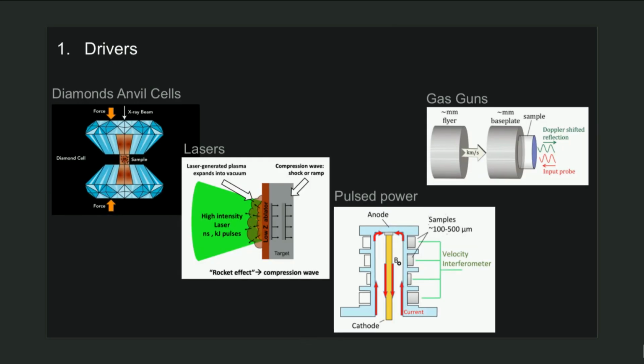So there are a few different ways to get to high pressure. I'll be focusing on dynamic compression with lasers in the end, but it's just one method. Diamond anvil cells are able to reach extremely high pressures now with developments in the double-stage diamond cell, toroidal DACs. And so the double stage, I believe, was able to reach over 1,200 GPa and get a diffraction pattern at room temperature. Gas guns can get you to a couple hundred GPa. And again, there's developments in pushing all of these techniques to higher and higher pressures.